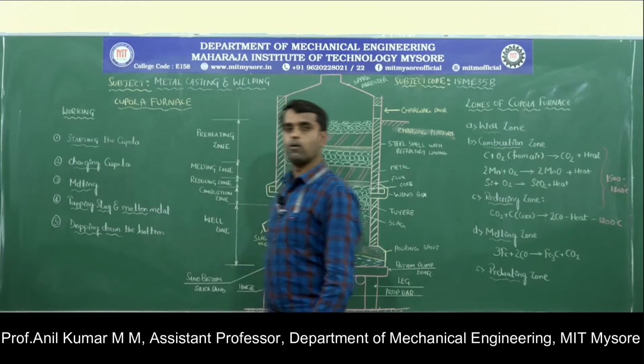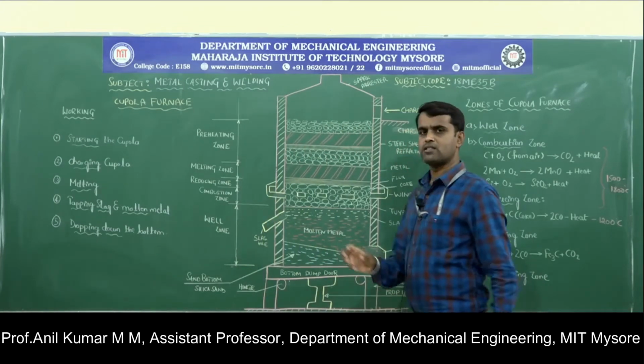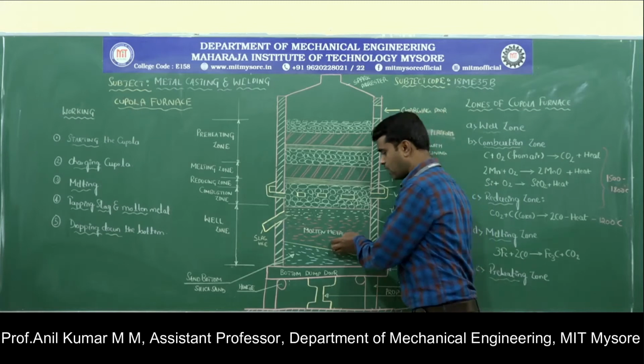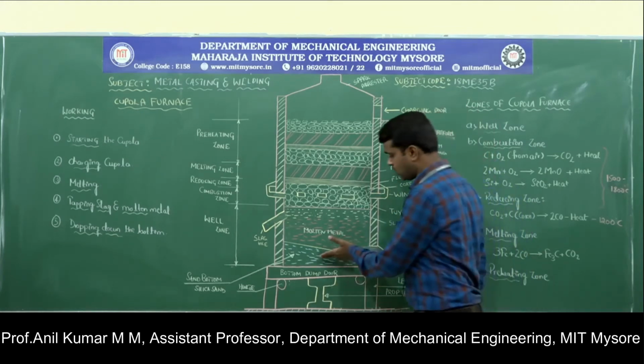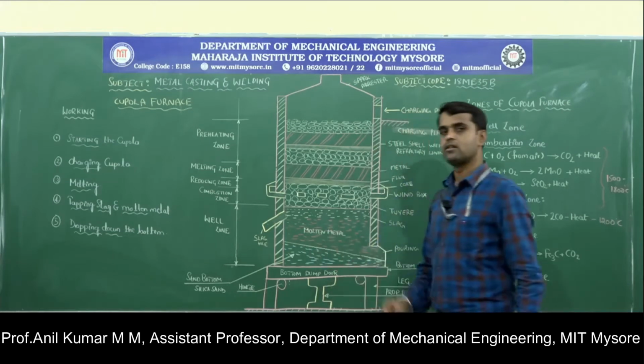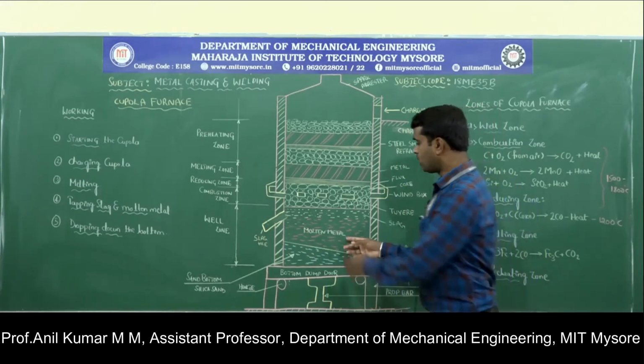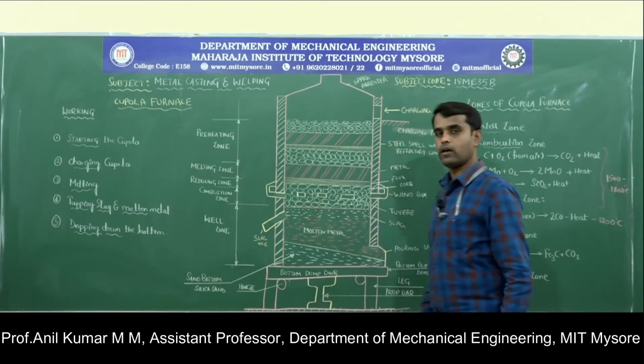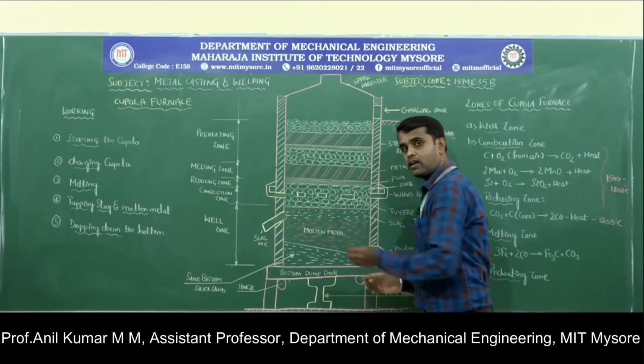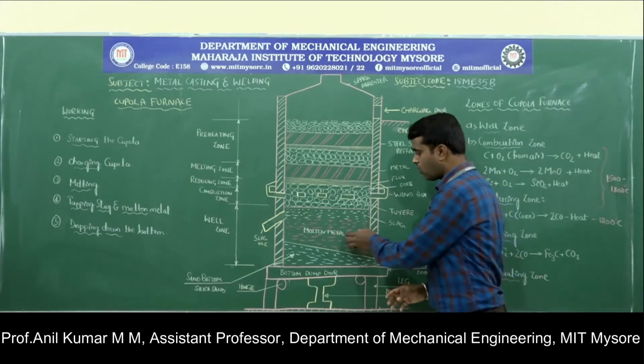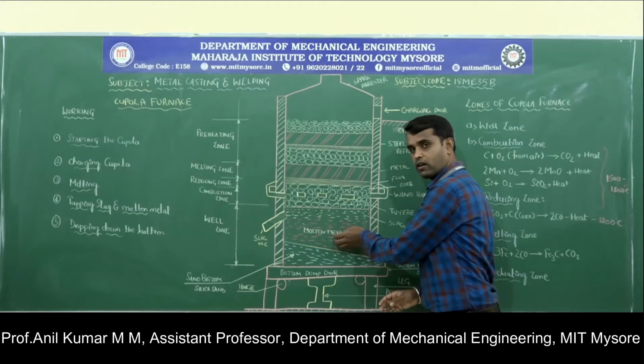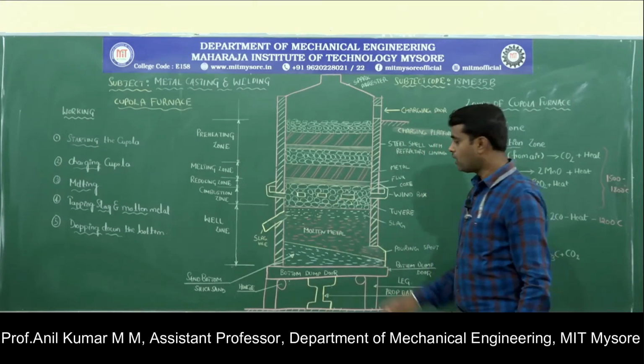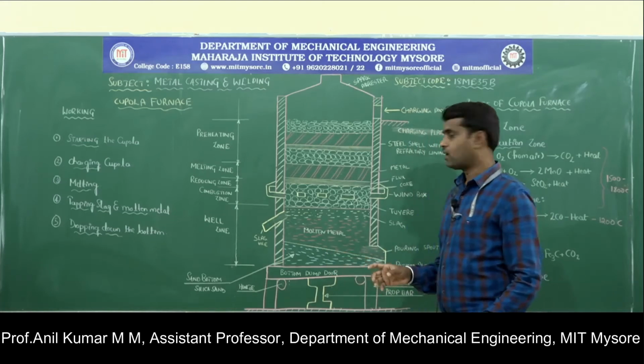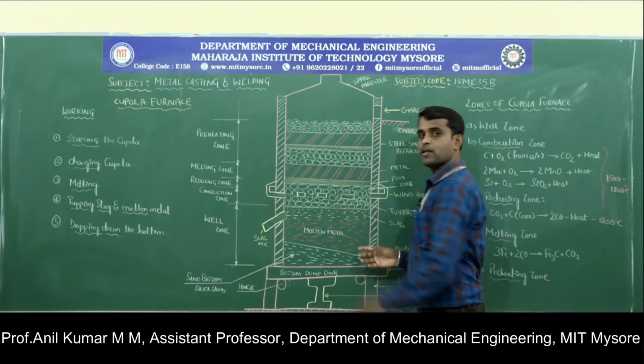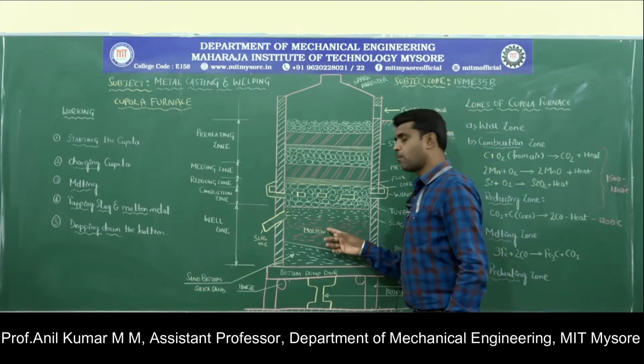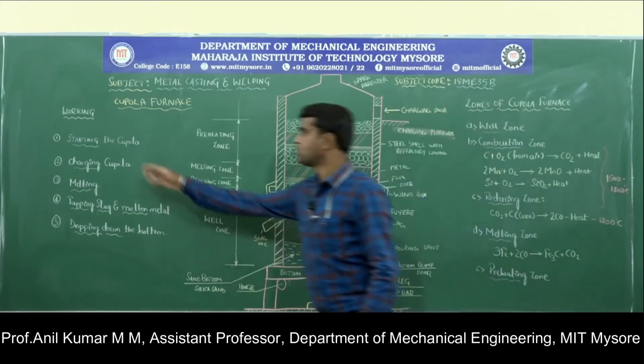First one is starting the cupola. Initially, we have to place soft and dry wooden pieces inside the furnace, slightly above the rammed sand. Okay, and then the coke up to the tuyere level. Add the soft and dry wooden pieces along with the coke up to the tuyere level, and then the wooden pieces will be ignited. Then you have to supply a suitable amount of compressed air inside the furnace so that combustion takes place.